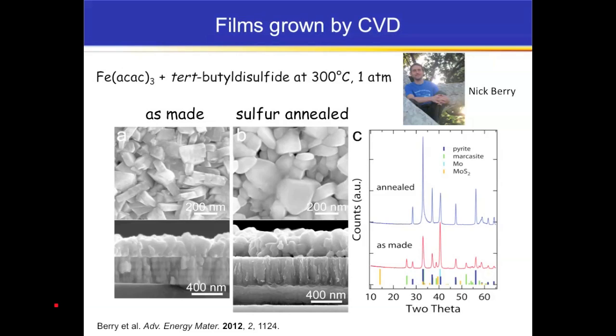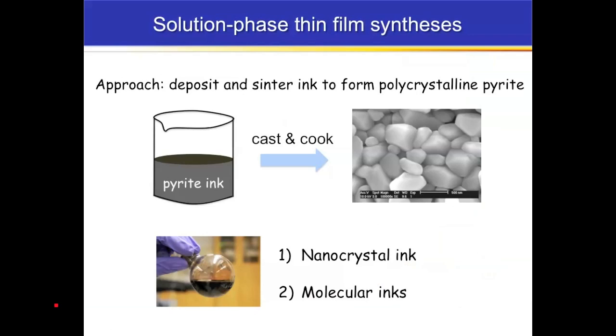It's important with pyrite to be very careful about phase purity and also elemental purity, so we go to great lengths to demonstrate phase purity. This is just XRD. We also use Raman spectroscopy and magnetic measurements. We basically throw everything we can at it, both for the phase purity and the elemental purity characterization. I'm not going to say anything more about the CVD films, except they're going to leak into one of the later slides.